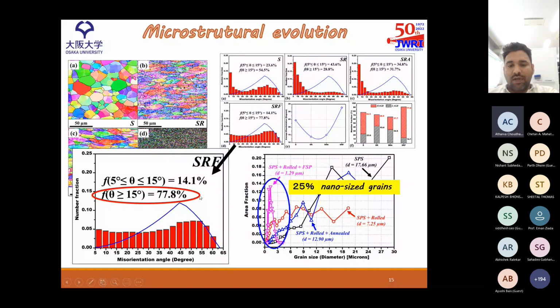Another proof which supports this statement of dynamic recrystallization, because it rarely happens in aluminium. Aluminium mostly shows recovery and not dynamic recrystallization. Recovery and CDRX are the most prominent mechanisms in aluminium. But here we can see that 25% of the grains are of nano size. These nano size grains, with this high fraction of HAGB, are difficult to form by continuous dynamic recrystallization. So we can definitely say that discontinuous dynamic recrystallization occurred here.